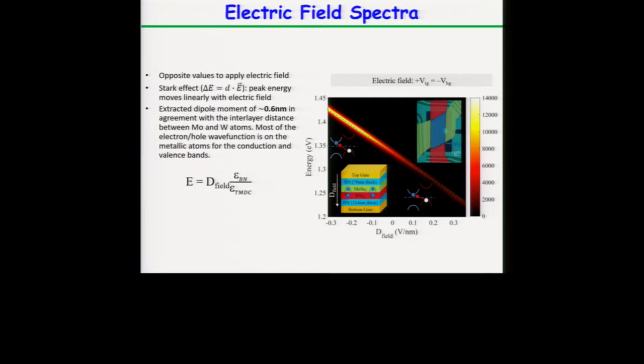But now if we use a different gate configuration, with one gate positive and the other negative, we have an electric field configuration. Since the electron is separated from the hole, in different materials, we can use an electric field to make them closer or to stretch them. That's what we did here. Using the displacement field, we can change the energy of the interlayer excitons by more than 200 meV, which is a large change. Even in gallium arsenide you cannot apply much electric field because the binding energy is small, so you start ripping them apart. But the binding energy of these interlayer excitons is large, around 150 meV, so you can still apply more electric field to keep changing the energy.